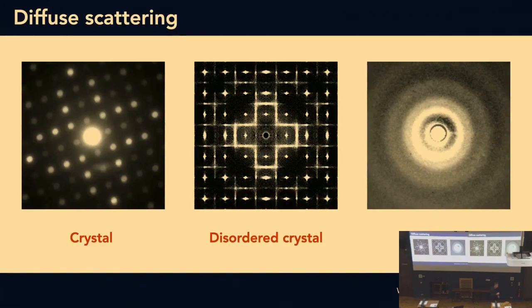Now, if I took something very disordered, like a liquid or a glass, and carried out the same experiment, the atoms don't know that they're not in a crystal. They still scatter the radiation. I still get an interference pattern. It just looks very different, and it would look something like this on the right-hand side. If the structure were truly random, you can show that this interference pattern would just be one single structureless blob, most intense in the middle and dying off. Here, we have what we'd call diffuse features, because these are very broad relative to the original spots.